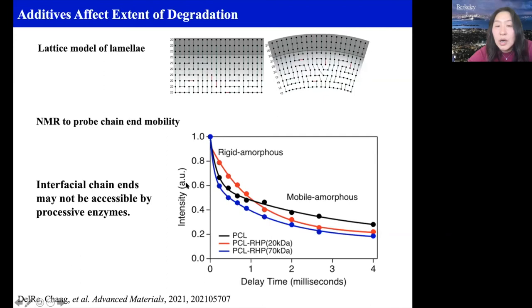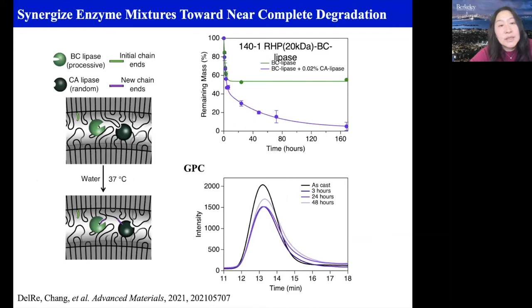So what can you do? This is what we see: we know that we have another enzyme with a surface exposed active site, and that can easily cleave the chain in the middle through random scission. And as it cleaves the polymer chain, it's going to produce a chain end that is far away from the interface, and that could be readily accessed by the enzyme. And that turned out to work really well.